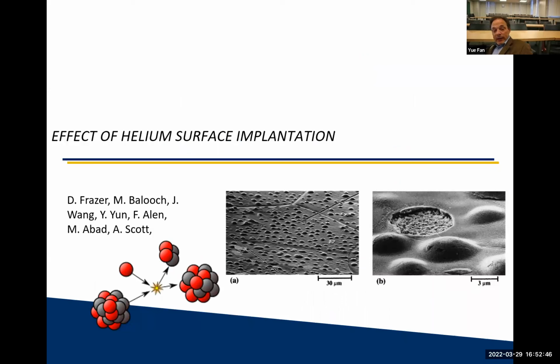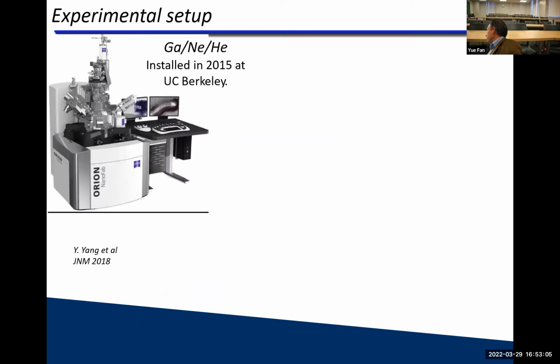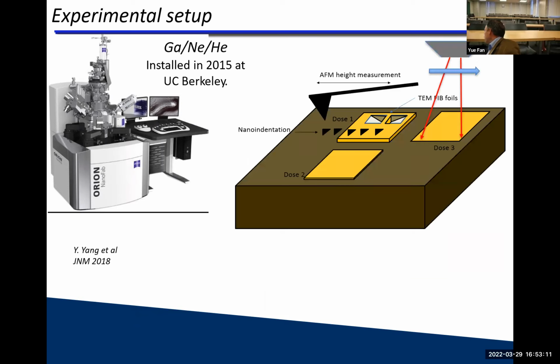Okay, and the last chapter I want to talk about is helium implantation. As I mentioned earlier, we talked about displacement damage, but there's also transmutation damage. And with transmutation damage, you create helium in materials and on surfaces. And here it is, for example, a blister. The way we do this is we have a helium ion beam microscope, and that implants helium in like 10 by 10 or so microns.